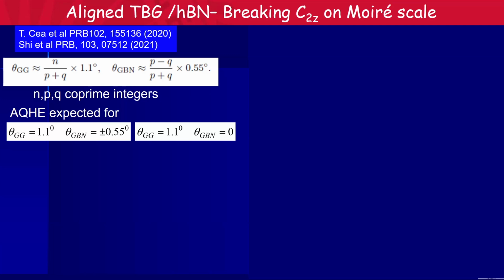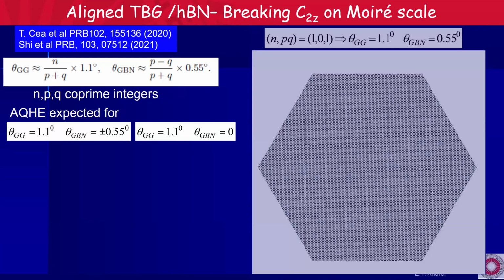However, how can we do that experimentally? And now I'm going to show you why this is so challenging. Experimentally, we know very well how to twist graphene on graphene, because we do it with the same graphene layer. We cut it in two, we superpose and we twist, but you can't do that with boron nitride. With boron nitride, it's very difficult to get a precise alignment. And here is an example.